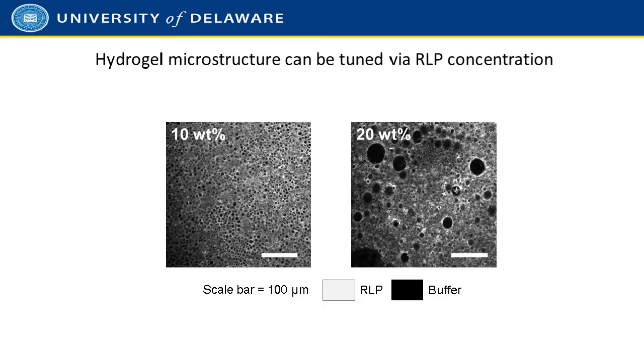The scale bar in these microscopy images, these are confocal microscopy images where the light color is the RLP, so we can pick the autofluorescence up of the Resilin-like domain. At low concentrations, the phase separation is slower, so the domain sizes are much smaller. When we increase the polymer concentration of the solutions, the polymers can phase separate more rapidly, so at a given point in time, we're able to capture domains on a size scale that are more commensurate with that of cells, which is on the order of tens to hundreds of microns.